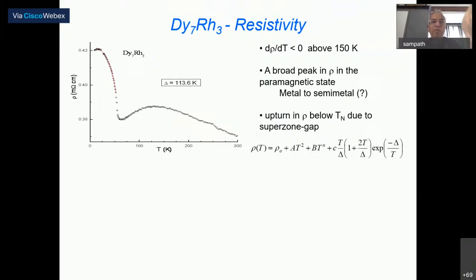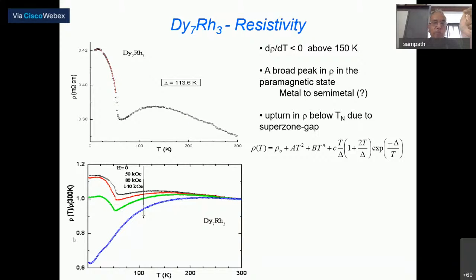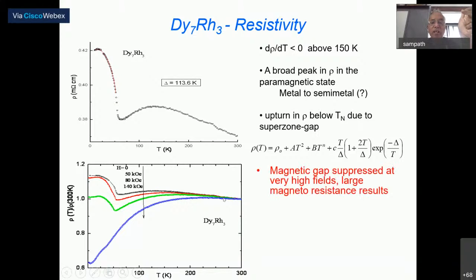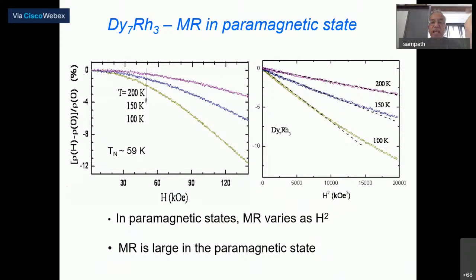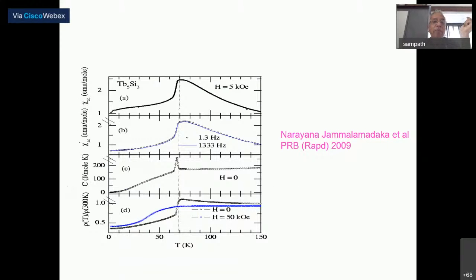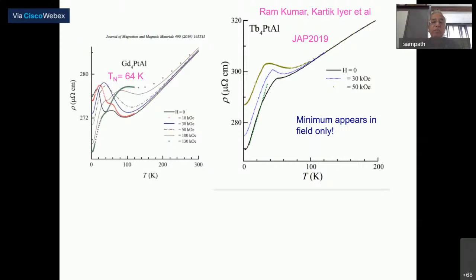Now, since dysprosium rhodium 3, there is another maximum here. You could see similar behavior, a very huge anomaly here, and it could be suppressed by the magnetic field. Right? This is even almost up to room temperature. And again, there's a very good scaling with magnetization. This one, again, terbium 5 silicon 3, you could see right from room temperature the negative temperature coefficient of resistivity here. Sorry, this one here. And this is a magnetic ordering at this temperature. So it's a completely different structure here. There is no frustration in this material.